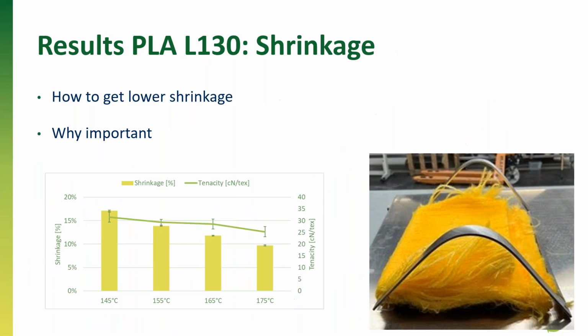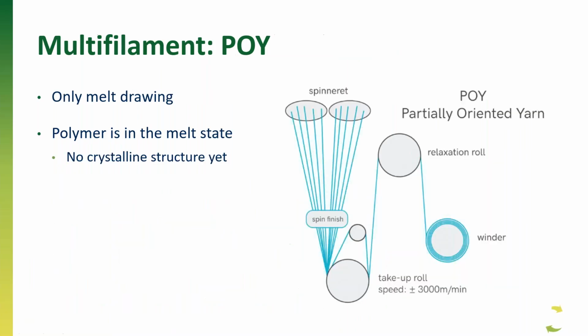You can see on the image right here that the frame is fully bent when Comfil is producing these filaments into organo sheets. It is very important to have a lower shrinkage, and this is not possible in this standard way of producing the filaments. You can see here the shrinkage that we have is over 15%, and we can get it lower to 10%, but then the strength of the yarn also lowers significantly. So what we are doing now is doing it in 2 steps.